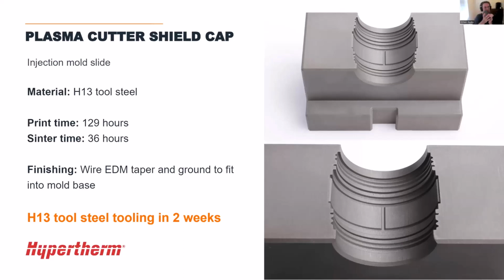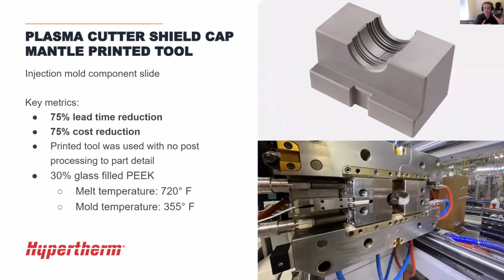This part was printed in 129 hours, so about 5 days here, sintered for 36 hours. After it was done through the sintering process, they had to do some wire EDM for a taper that's on the side of this, as well as they ground it to fit it into the mold base. But after all that was done, they had H13 tool steel tooling in just 2 weeks, which of course is, if you're familiar with tool steel tooling, a very, very fast process here to get them the slide in just 2 weeks. What are some of the key metrics here?